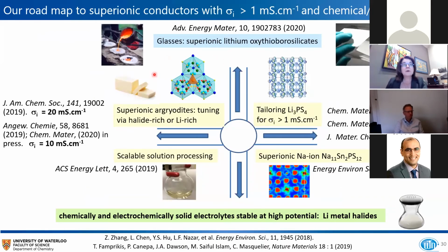So in our group, we've looked at many different approaches, not just the paddle wheel, which is how to turn on paddle wheel effects, but also how to design materials that have superionic conductivity, which is defined as greater than 1 millisiemens per centimeter. And also trying to design conductors that have chemical and electrochemical stability. So we've developed some new superionic glasses, and these allow melt processing. These are lithium oxythioborosilicates, which actually are fairly stable to moisture, which is certainly a benefit.